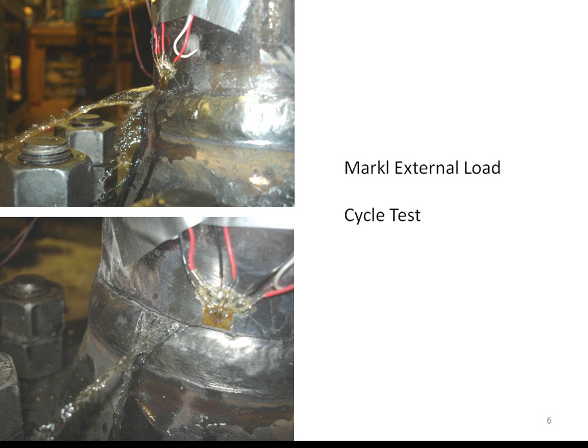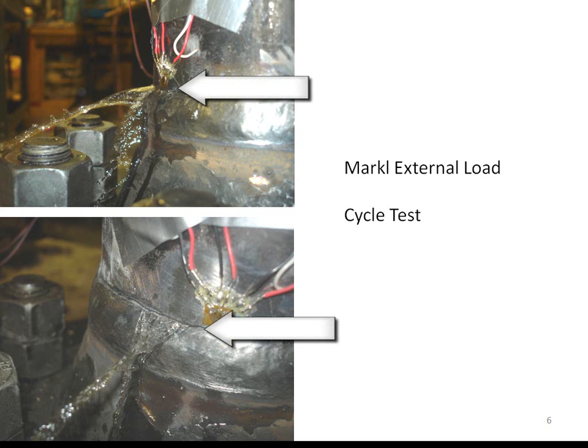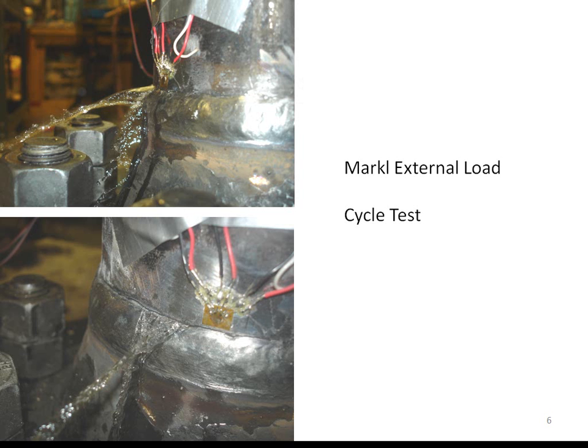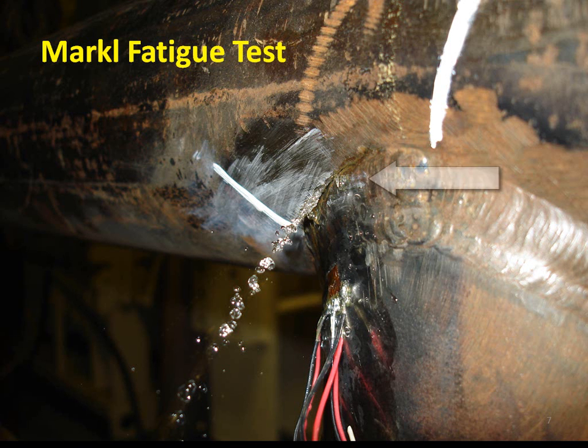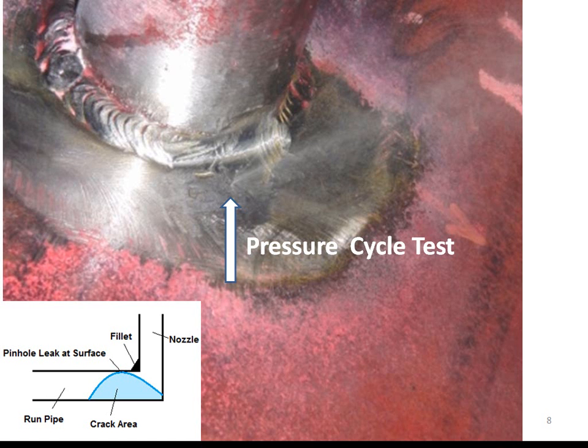The crack and leaks here are at the toe of a girth weld at the flanged base of a 4-inch standard wall carbon steel pipe in a Markl fatigue test. The cantilever in the test is repeatedly flexed in bending a fixed distance until water appears at the base of the test. Here's another Markl fatigue crack leak at a 4-inch standard wall unreinforced intersection weld.